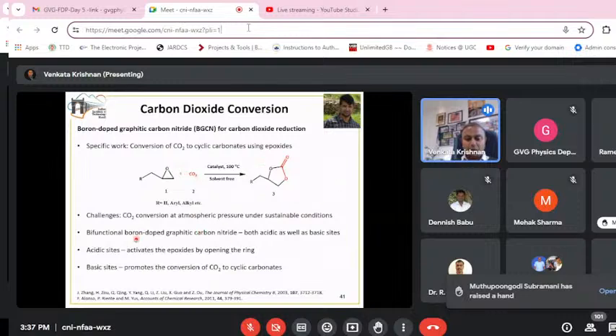How we have done it: we have a bifunctional boron-doped graphitic carbon nitride catalyst, which has both acidic sites and basic sites. The acidic sites come from the boron atom in the catalyst, and the basic sites come from the nitrogen atom present in the carbon nitride group.